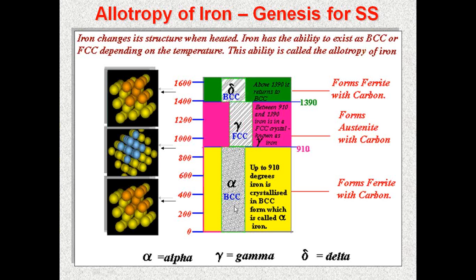Allotropy is the ability to change structure as you heat the element. You can see here that iron is available from room temperature up to 910 degrees as the alpha phase. That's the body centered cubic, as you see in the structure. Then you go to the gamma phase from 910 to about 1390. You have the gamma phase, which is an FCC structure, face centered cubic. This is called austenite and this is called ferrite. Now as you go to 1390 toward melting, you form a delta structure, which is body centered cubic and is also called the ferrite structure. This is the structure with carbon. So if you are able to retain this structure, you have a ferrite structure. If you are able to retain this gamma structure, it is an austenite structure. This delta is formed particularly during welding and other treatments.